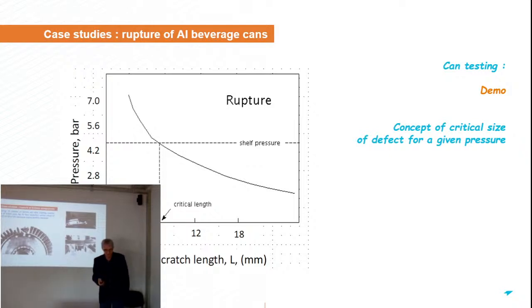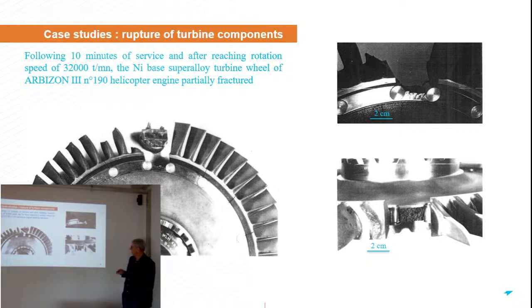Okay, another example here, which is more connected with the aerospace industry, which is the domain in which I work preferentially. So here you have a turbine wheel of a helicopter engine. This is made with a nickel-based superalloy, and we suffered this fracture here of a blade, you can see here, after 10 minutes of service, a very short time of service, and after the rotation speed reached 32,000 rotations per minute. This is the helicopter engine produced by a French company, a Safran helicopter engine.